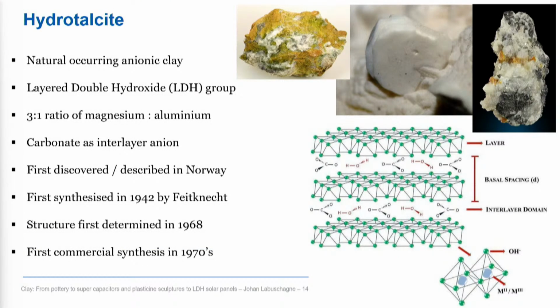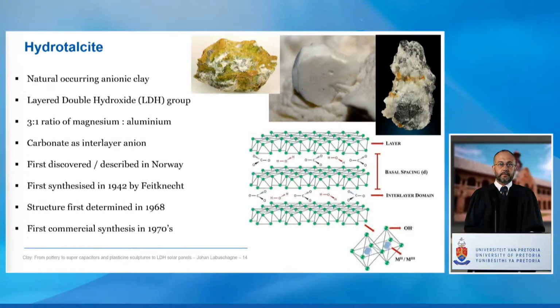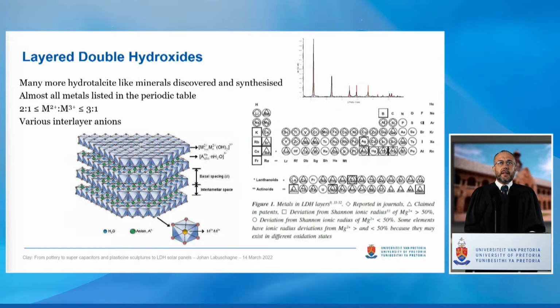Typically, these clays are made up of a 3-to-1 ratio of a divalent metal, magnesium, and a trivalent metal, aluminium, with a counter-ion as carbonate to make sure that the layered structure is balanced in charge. During the 1970s, it was used as a catalyst, and in medicine, it's used as an antacid called Maalox, which led to its commercial synthesis. Here we can see another schematic of the structure, but in a general form. So we are not showing the magnesium and aluminium as the 2- and 3-valent metals and the anion carbonate, but a general 2-valent, 3-valent symbol and A for the anions.